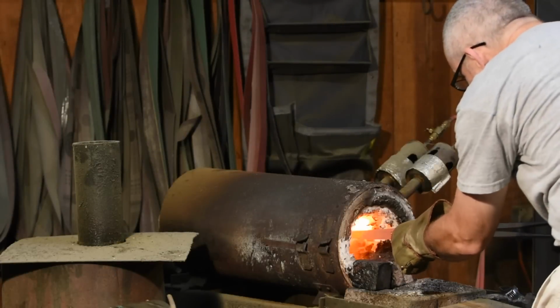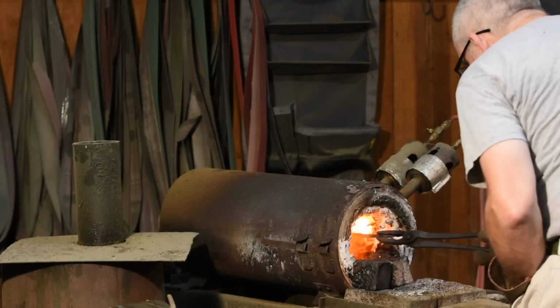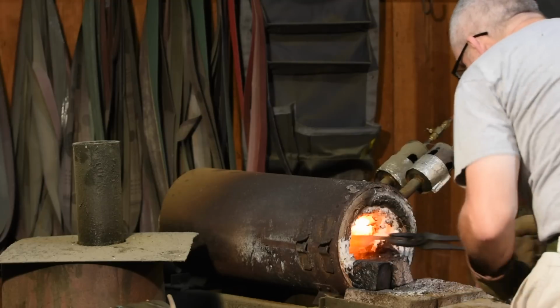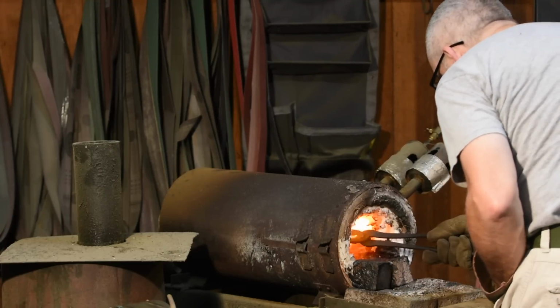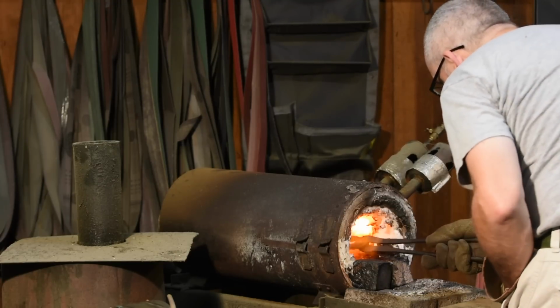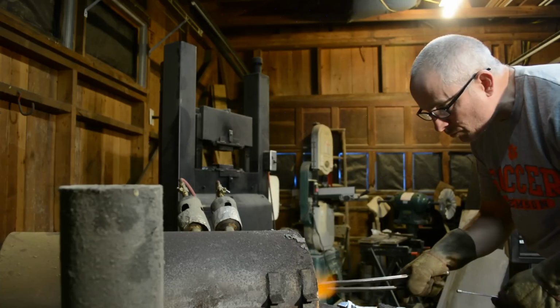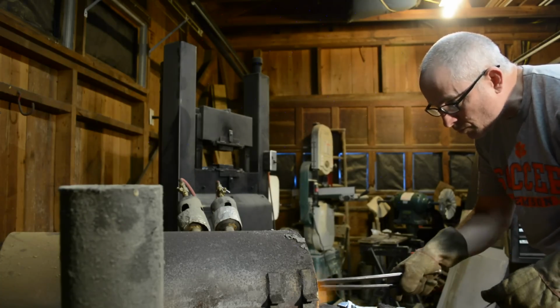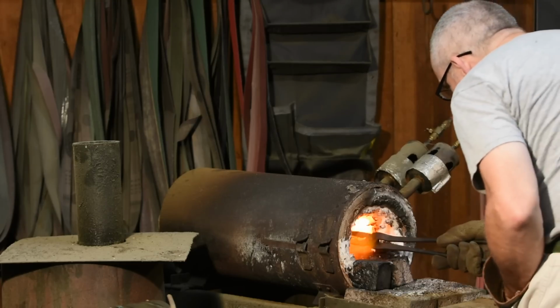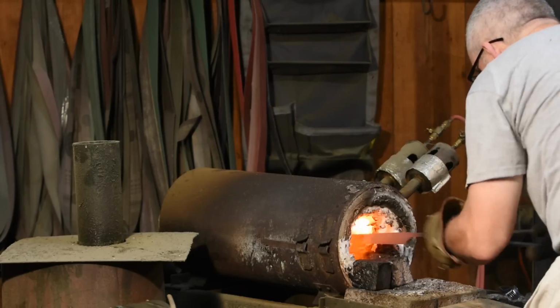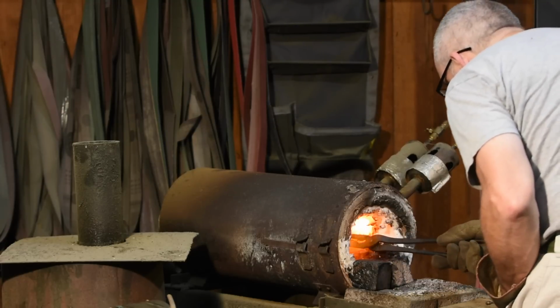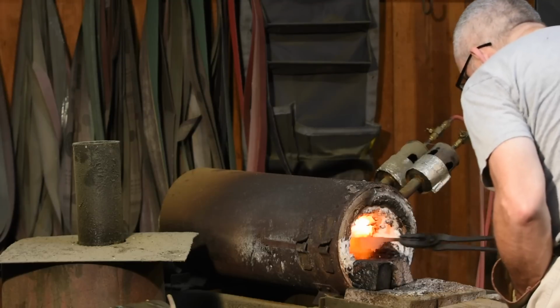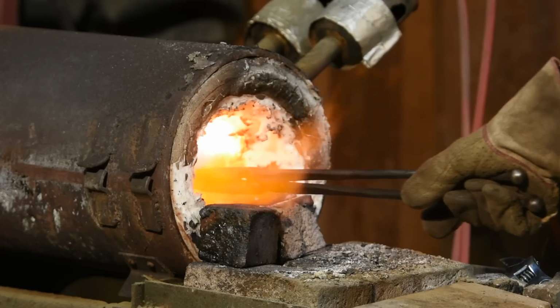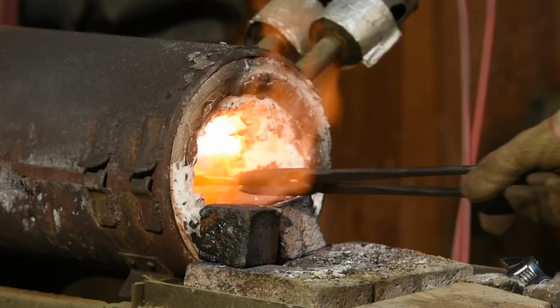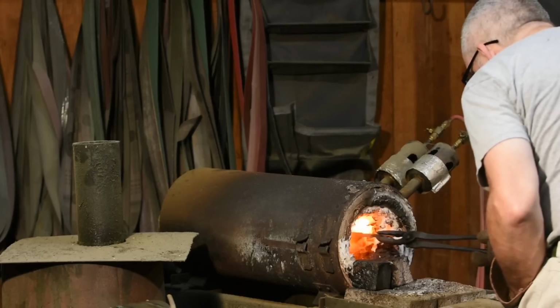Once the geometry is where I want it, I'll go ahead and heat treat the blade. The forge is brought to temperature, and then the knife is heat treated to roughly 1500 degrees Fahrenheit. I'm using a magnet to detect the temperature. At about 1425 Fahrenheit, steel loses its magnetic properties, so I know that once I get a little bit over that, I'm getting close to my goal. So just let it creep up a little bit and make sure the entire blade is brought to temperature.